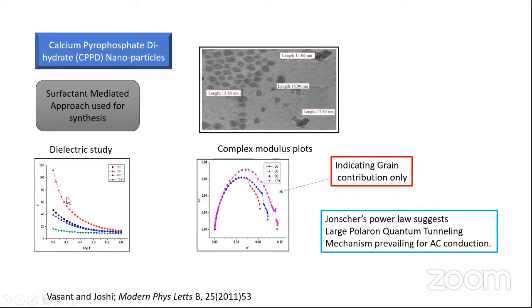At low frequency, different types of polarizations are effective, and that is why they show a higher dielectric constant, and at high frequency they show almost the same or saturation value. Another part is the complex modulus plots, where the real and imaginary parts of the electrical modulus are plotted. They show the grain and grain boundary. Here only one semicircle is observed, and that shows the grain effect only. From this dielectric study, one can apply Jonscher's power law, and from the different parameters obtained at different temperatures, one can identify which type of mechanism is prevailing. The large polaron quantum tunneling mechanism is prevailing for AC conduction.